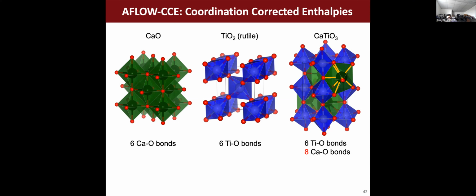So getting back to the slide, there are some corrections that exist in the literature which are only dependent on the composition of the material. They don't consider structural aspects of the material, which include coordination. This correction scheme takes into account not only composition but also coordination. Let me give you an example. If I'm looking at calcium oxide, we have calcium in the middle and oxygen sitting around it. It's going to be six-fold coordinated with oxygen.